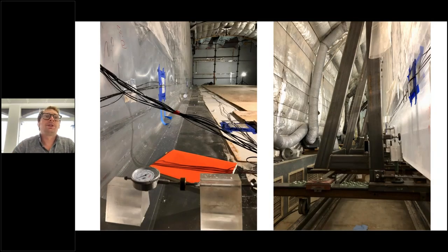And then you can see the bonding, which has taken place on the left-hand side. And this was a critical aspect for the construction, and one most difficult to control for a structure of this size and weight. So the syrup, as it starts to cure. So the bond we're looking at in this case is the longitudinal bond running underneath my notebook here. And you can see the dial gauges looking across the gap. And so when the syrup is poured in, it heats up and it expands. But a short period after that, it goes through a much longer period of contraction. And so if we're not letting these two components move together, we're introducing stress and strain into the material, which can cause bubbles. Obviously, you know, from a visual perspective and from a structural perspective, that's not good.